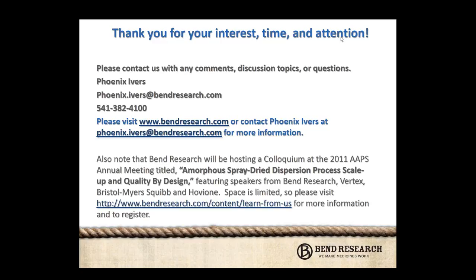Go ahead. I guess initially, of course, what you want to do is somewhat maximize throughput, and so you need to have a solvent that you have reasonable solubility of both drug and polymer. It needs to be a fairly volatile solvent or solvent mixture. So the ideal ones are kind of acetone or methanol. THF oftentimes is a solvent that we'll use if we can't get good solubility of the drug and polymer in acetone or methanol, and then sometimes the addition of a little bit of water can help with solubility.